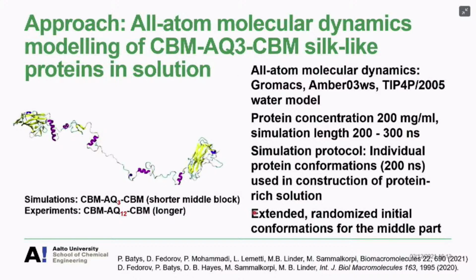Methodology is listed here. In simple terms, these are GROMACS simulations, atomistic detail molecular dynamics simulations, and we are matching the experimental protein concentration, which is 200 milligrams per milliliter in that cryo-TEM image, also in the microscopy image that you saw, and in some other data that you are going to see later on. Individual simulations are 200 to 300 nanoseconds, which is not a huge amount for intrinsically disordered proteins. I'm going to comment on that later. We are doing both individual proteins and then constructing multi-protein constructs based on those. The initial configurations are quite extended so that they can really fold to whatever they would want to fold, but they do not reach equilibrium in those 200 or 300 nanoseconds.